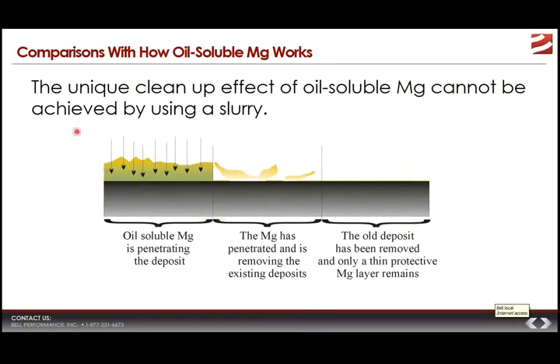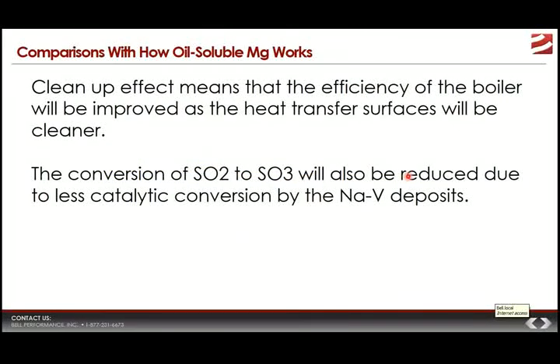The oil-soluble magnesium actually does not form a layer on top of the deposit. It actually will penetrate the deposit. It will go into the deposit, and then it will start to react, and it will start to change its morphology and change its physical characteristics from the inside out. And so over time, the oil-soluble magnesium actually helps to penetrate and remove the existing deposits because of the way it changes their physical characteristics. So they drop off. The old deposit's been removed, and all you have is a thin layer of magnesium that remains. You now have the optimal solution for getting the best results with your system.